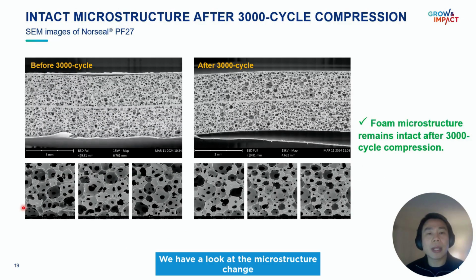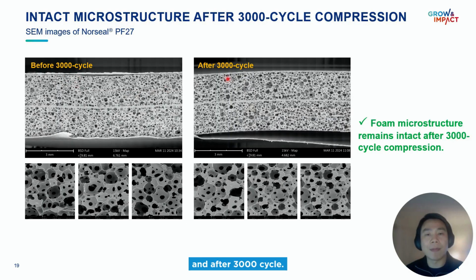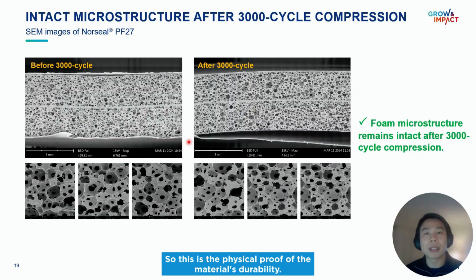We have looked at the microstructure change of these compression pads under extreme conditions. Side by side, we can see the SEM images before 3000 cycle and after 3000 cycle. As you can see, the foam microstructure remains completely intact. The cells has not collapsed or damaged. So this is the physical proof of the material's durability.